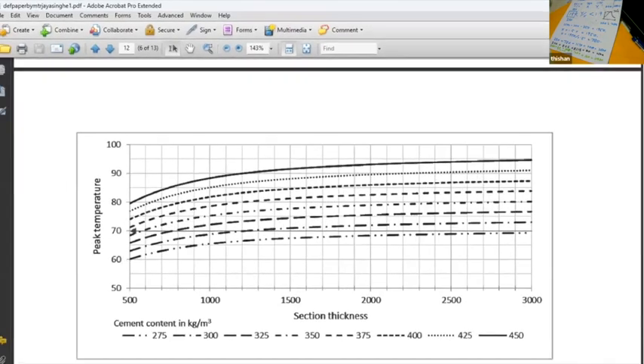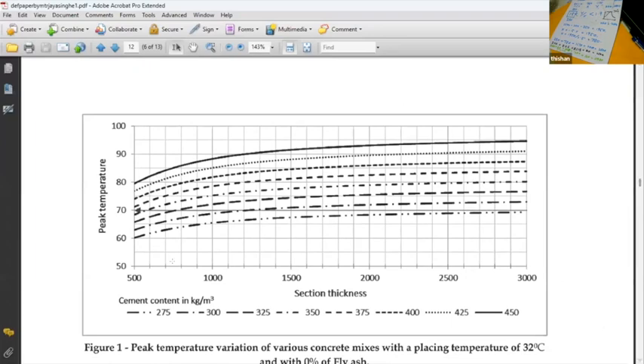What it says is, if you are using 275 kilograms of cement, whatever the thickness of section, the temperature will remain less than 70 degrees. So this is a peak temperature. On this side is section thickness. We are using no fly ash, and the placing temperature is 32. So you can see, whatever the thickness, even 3 meter thickness, the temperature remains less than 70 degrees when you use 275 cement.